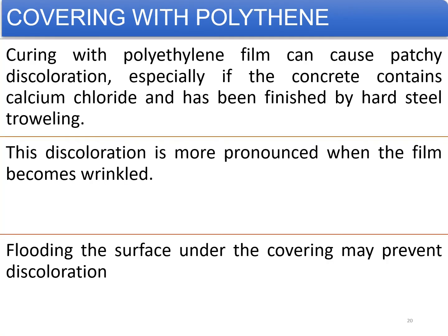Curing with polythene films can cause patchy discolorations, especially if the concrete contains calcium chloride and has been finished by hard steel troweling. This discoloration is more pronounced when the film becomes wrinkled or folded. Flooding the surface under the covering may prevent such discolorations, because this will almost minimize the wrinkling effect of the polythene sheets.